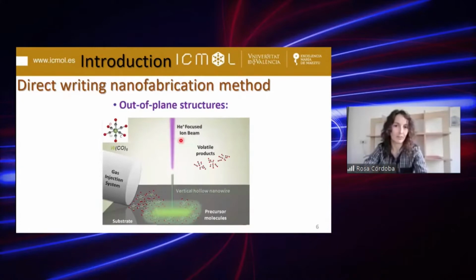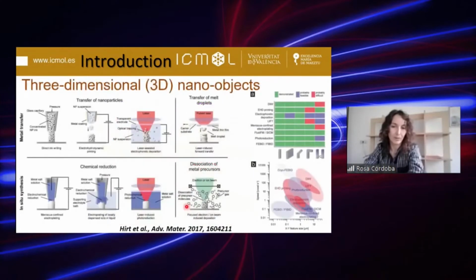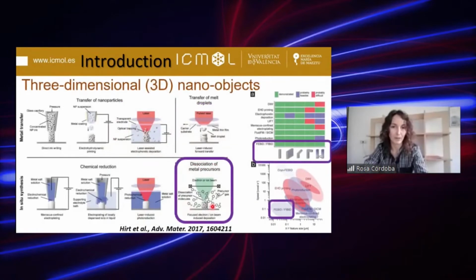No, it's not going. Okay, it seems very slow. So the method to draw three-dimensional nanostructures is the same, but the beam strategy is quite different. In this case, I show one sketch of a vertical nanowire, a nanopillar, but if we modify the scanning parameters, we can create more complex structures like nanohelices. And I would like to remark that focused ion beam induced deposition is one of the most promising techniques for the fabrication of 3D nano-objects, mainly due to its flexibility in the shape of the structures that we can create and the extremely high resolution that we can get.